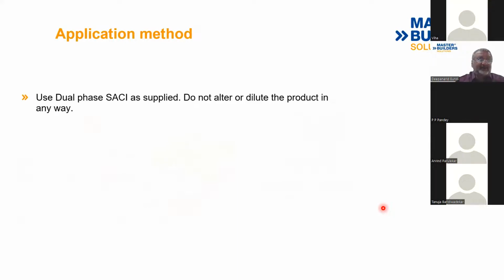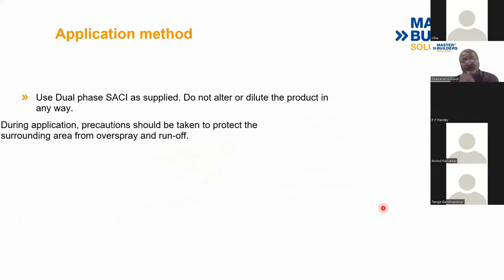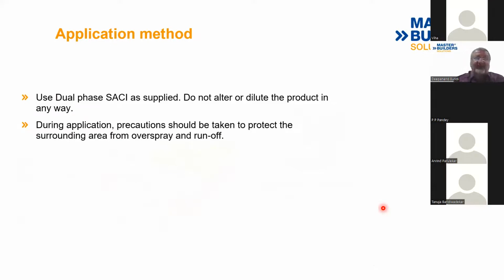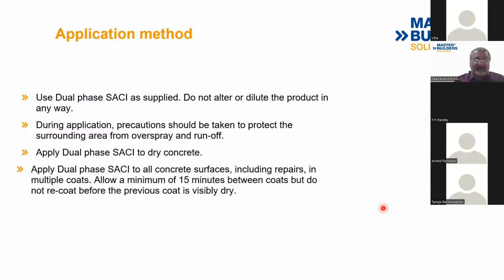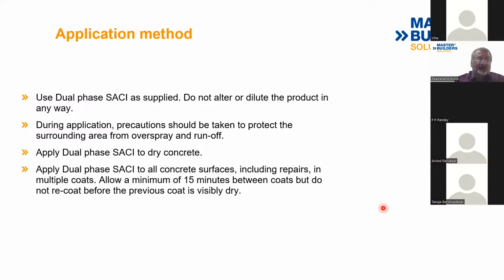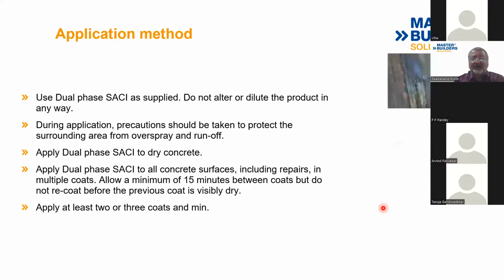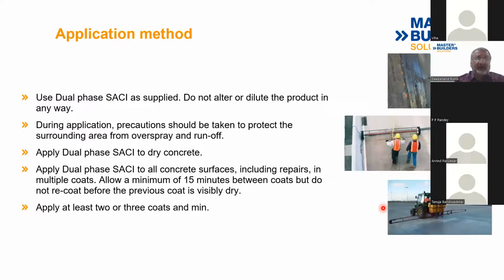The application methodology is pretty simple. Open it as it is. There is no dilution. It's a ready-to-use material, so at site there is not much of an issue. Protect surrounding areas in case of overspray, and apply it on dry concrete, as I said, for better penetration. Allow it to penetrate, and after 15 to 20 minutes, you can apply the second coat. Generally, we recommend a minimum of 2 coats for any protective coating system. In highly exposed conditions like coastal regions, apply an additional coat for better penetration.